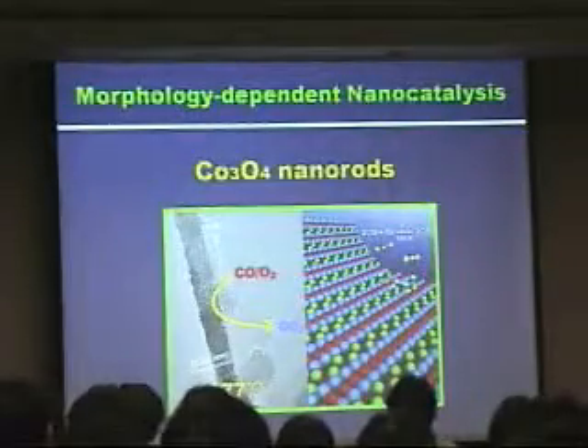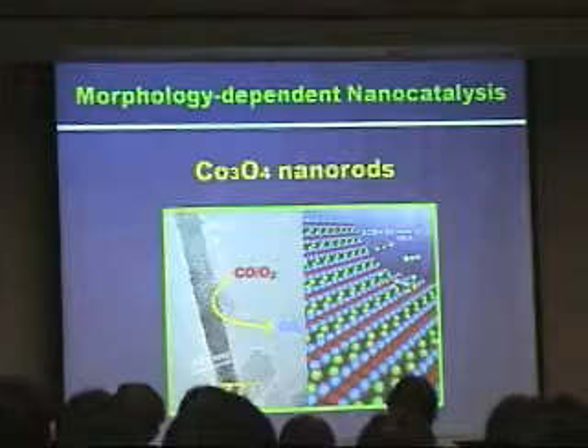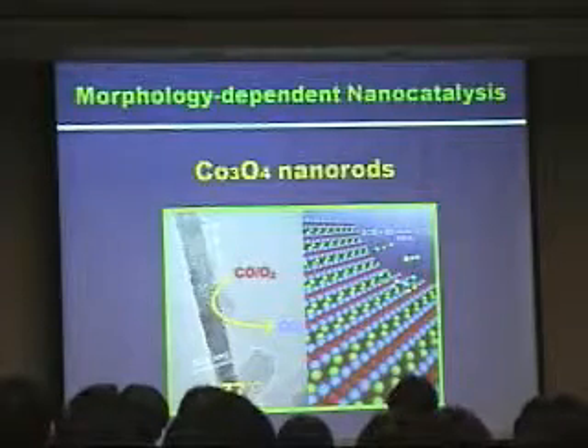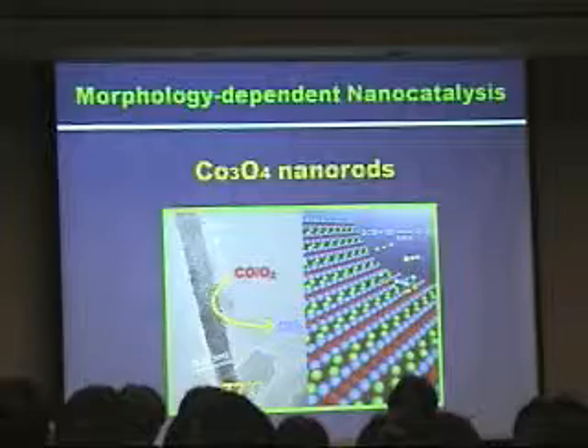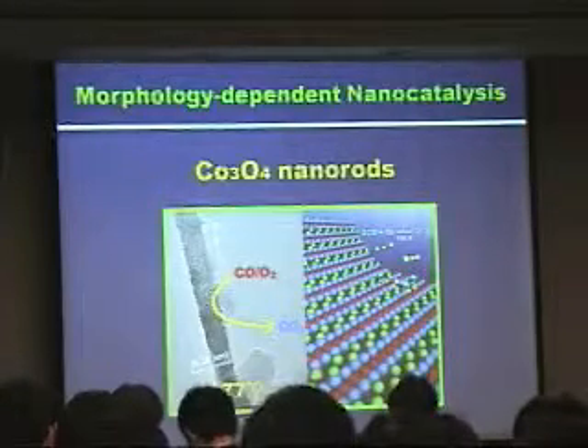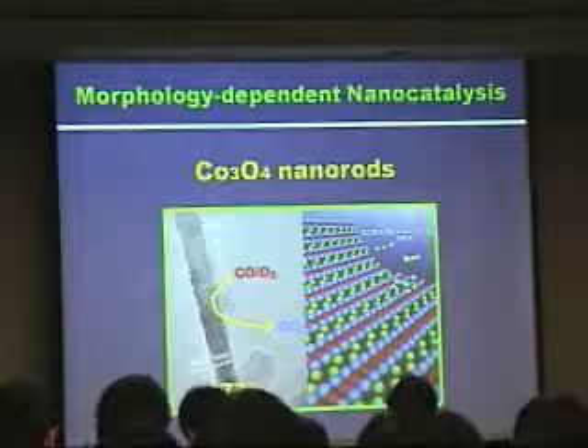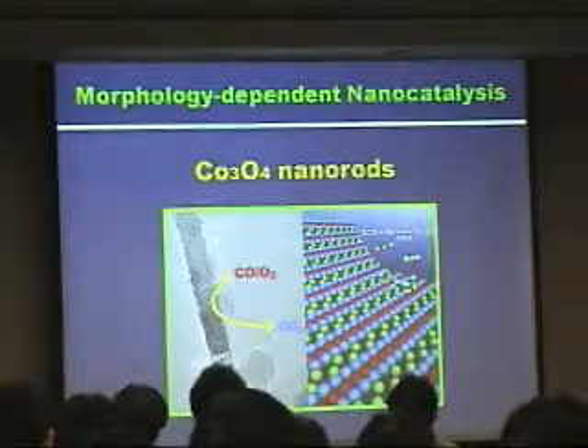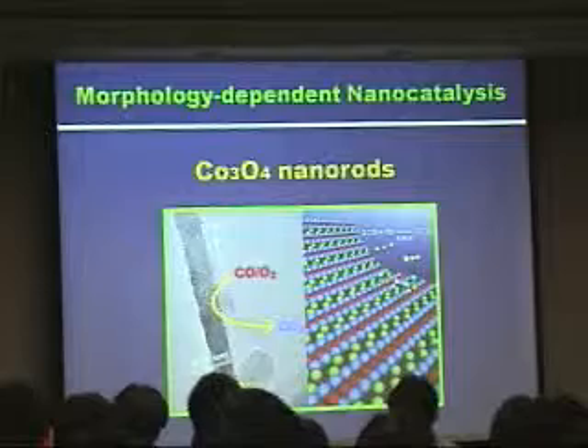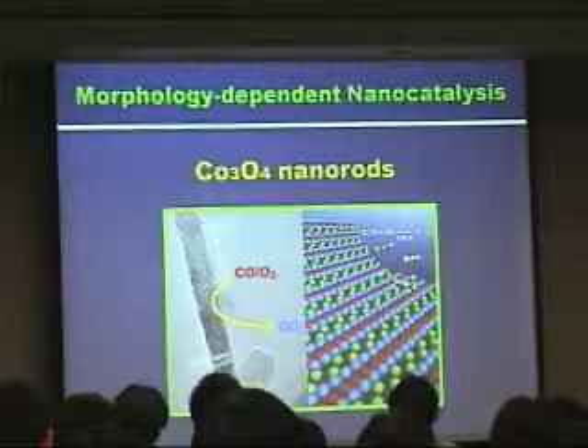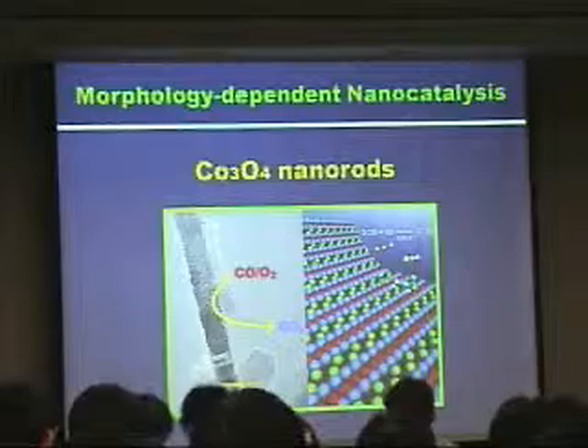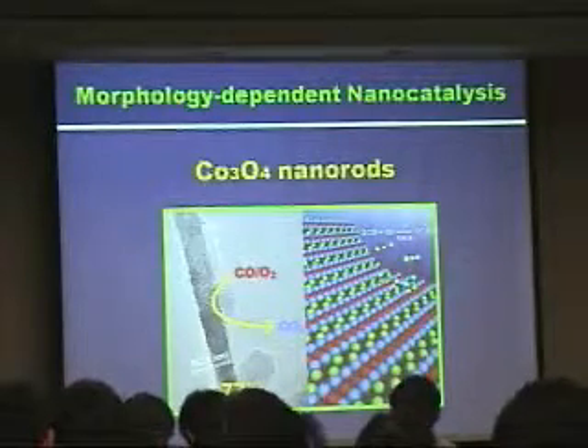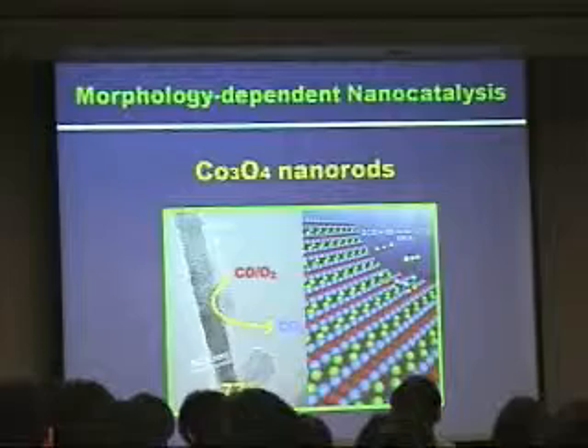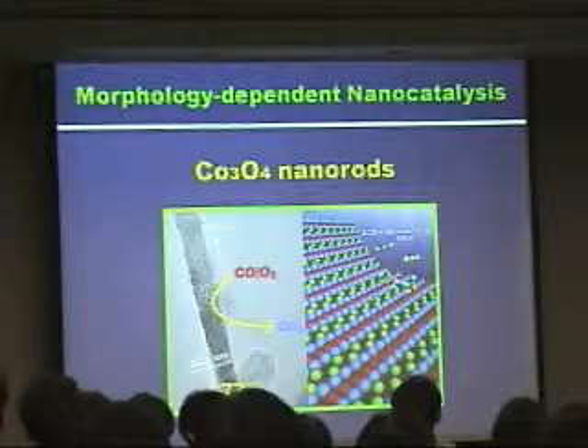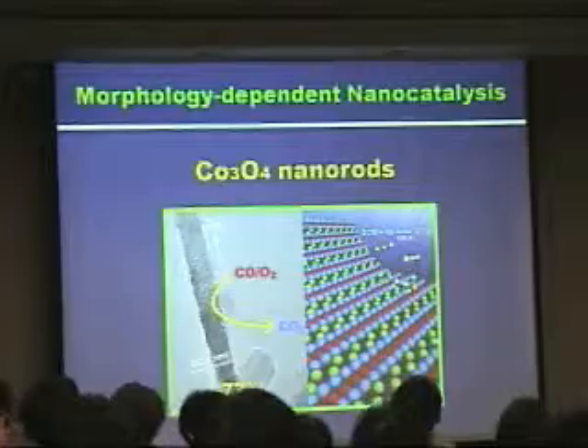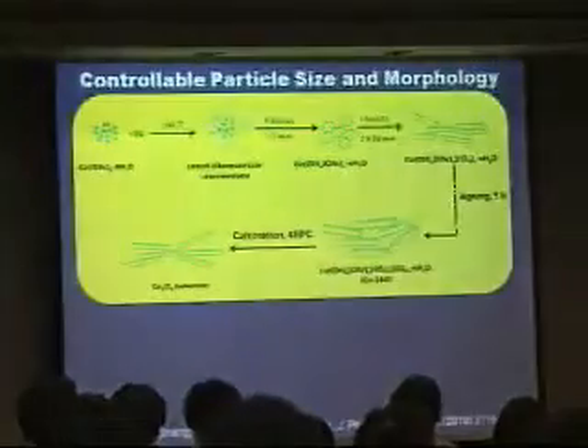Okay, we start from this typical example, cobalt oxide. This is widely used for CO oxidation reaction for many years. And usually most people use the spherical particles and decrease the size, and also observe the increase of the conversion rate. And when we change the shape at this small diameter into nanorods, we find a very significant change in the activity performance. So we started from the solution chemistry to control the shape of this material.